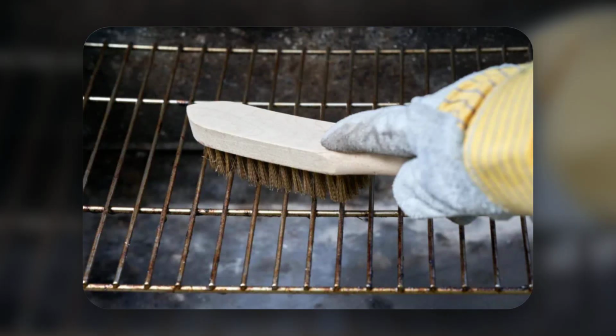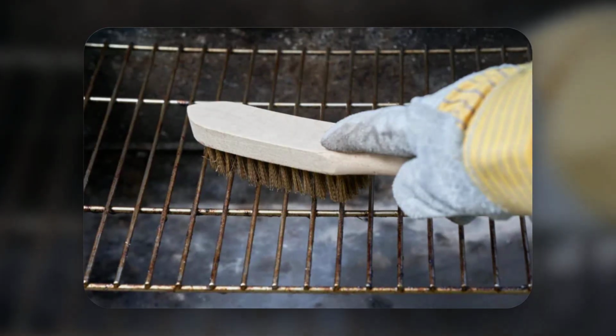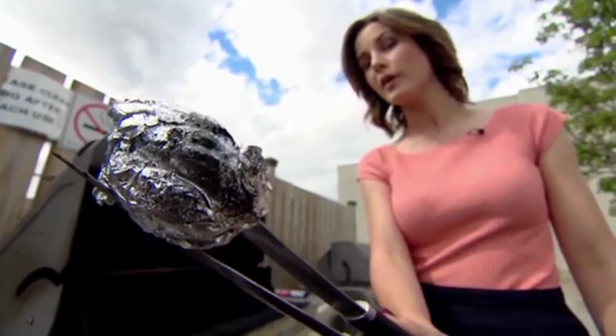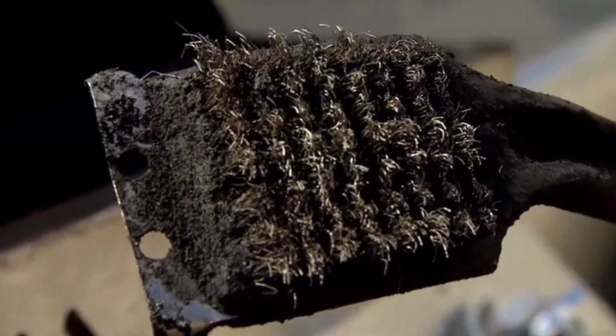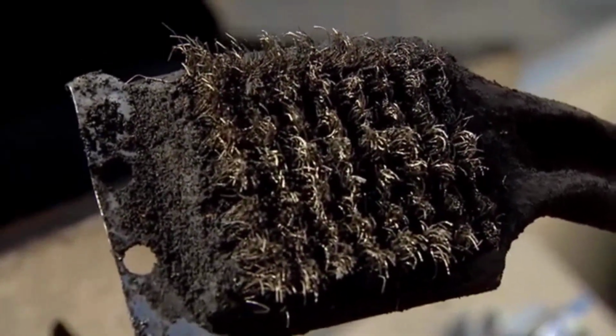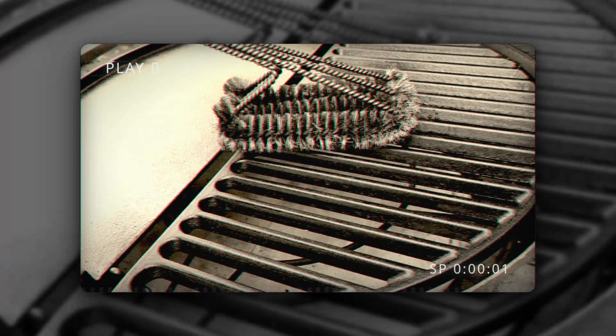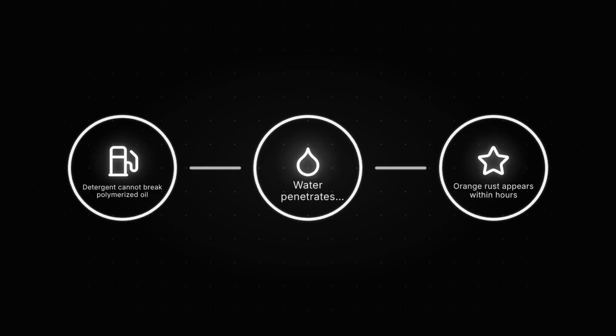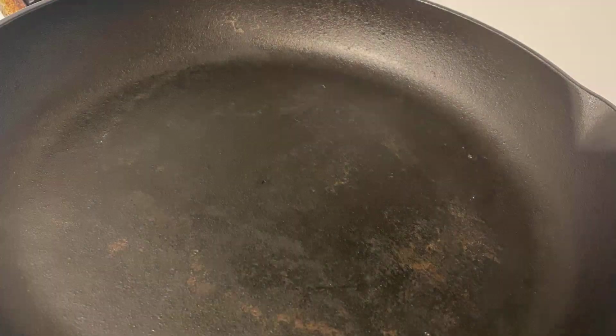It shortens its life. Overnight soaking in soapy water. 2 failures at once. Detergent cannot break polymerized oil, so the black layer will still be there in the morning. And hours of submersion is the worst possible treatment for cast iron. Water gets into the pores and under any remaining seasoning, and a soaked cast iron grate can show orange rust within a few hours of coming out of the tub. People do this, see rust, and conclude the grate was finished. The soak finished it.